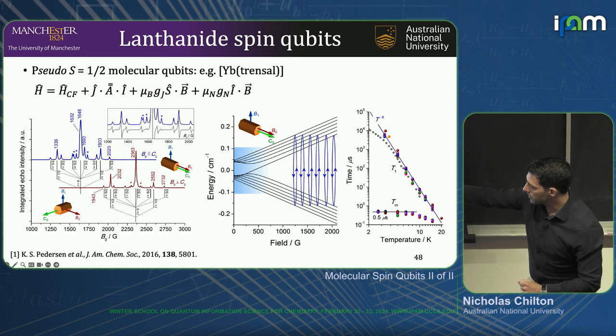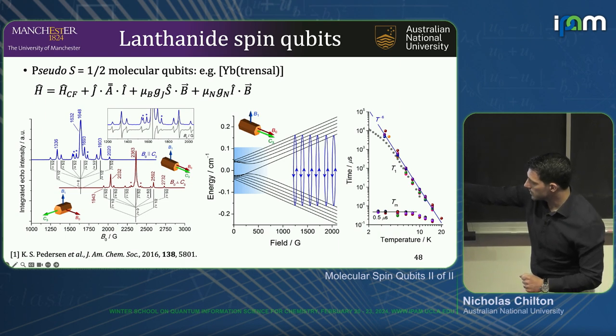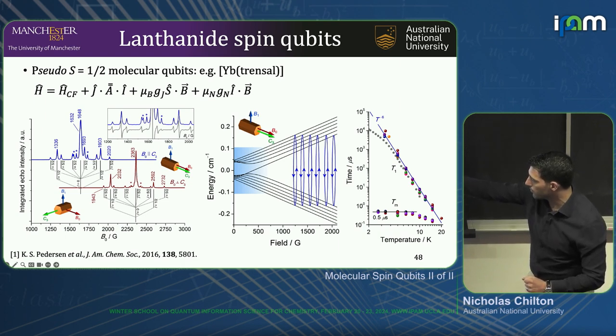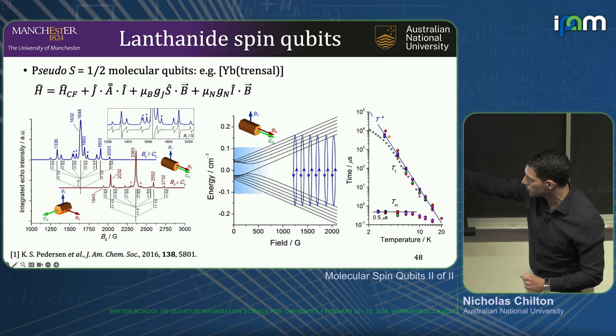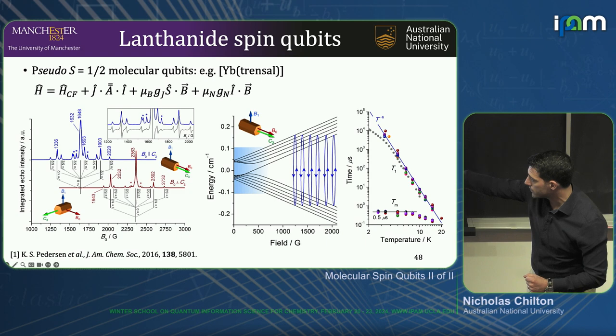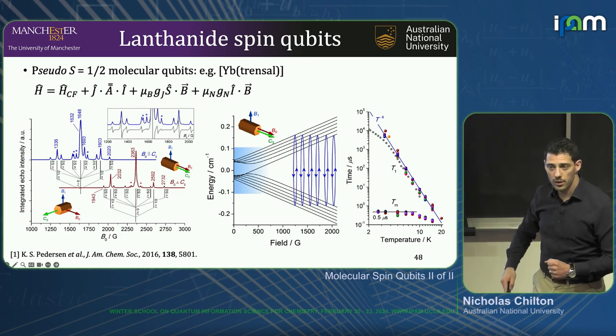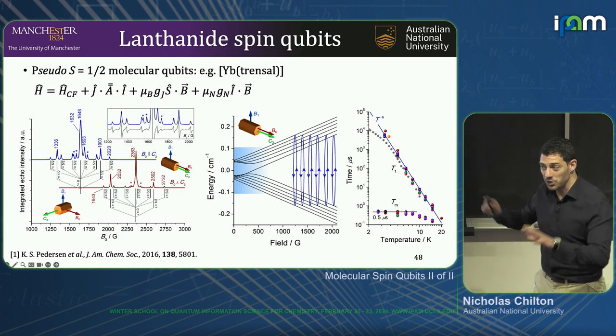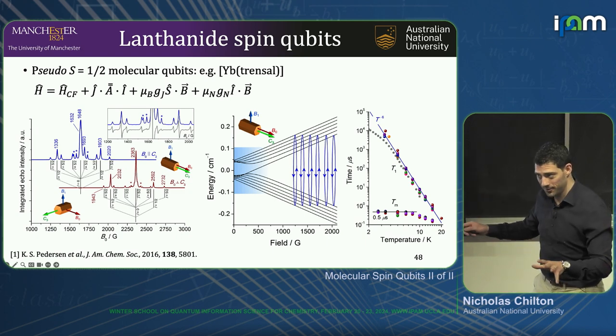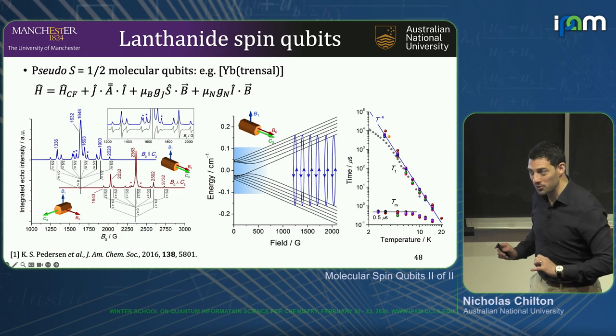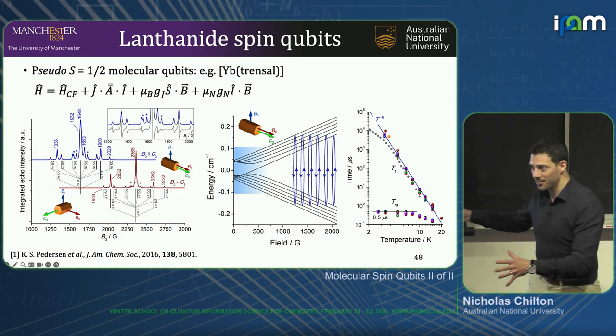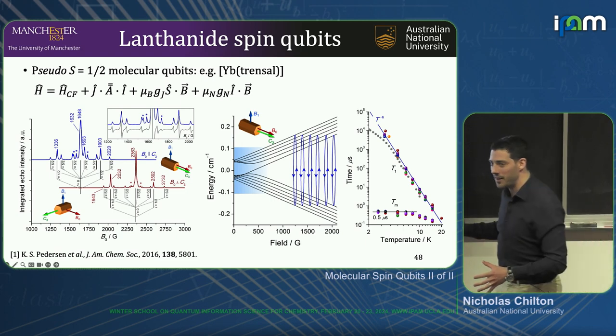With the field parallel to the symmetry axis, you get a nice splitting pattern. This indicates where some of the resonances are — the different hyperfine lines for a given nuclear spin. The central I=0 line branches; those hyperfine-coupled to the spin-1/2 nucleus give two lines, and the spin-5/2 lines are spread further out. That was a lot, I know — I'm trying to go quickly because this is just one example among many.